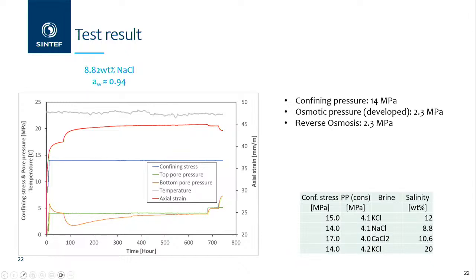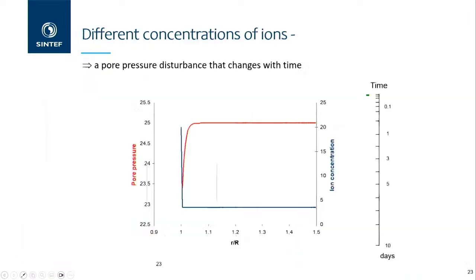So this test is with sodium chloride. It's understandable that sodium replacing sodium is not really a big issue. The pressure went down, but when I exposed it to the water, it came back. But that is not the case with KCl, because the KCl ion is smaller. When it goes into the lattice, it shrinks. It doesn't really want to come back to expansion again.